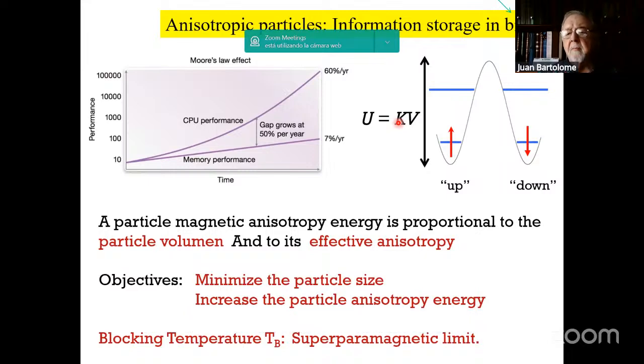Of course, to maximize the density of memory elements, we want to reduce the volume of the particles, and then we need to increase the anisotropy. This game has been very effective, and there has been an increase, doubling the density almost per year. That's called Moore's law. But this game has a limit.